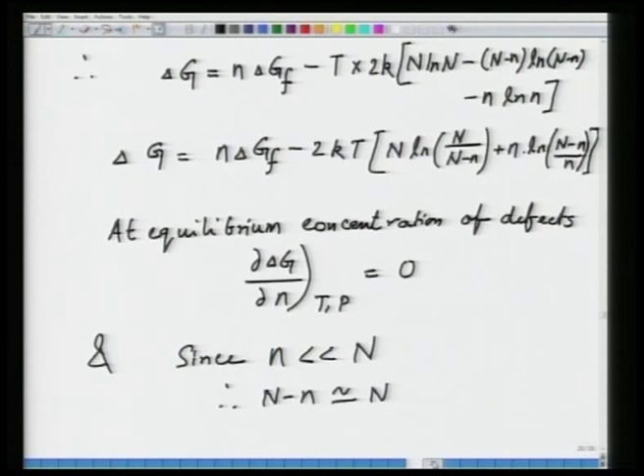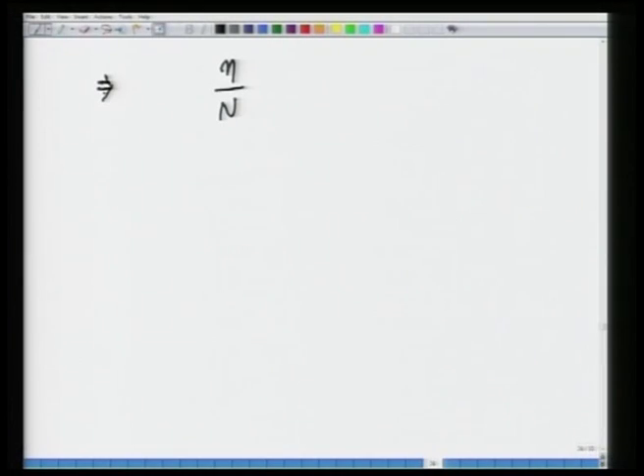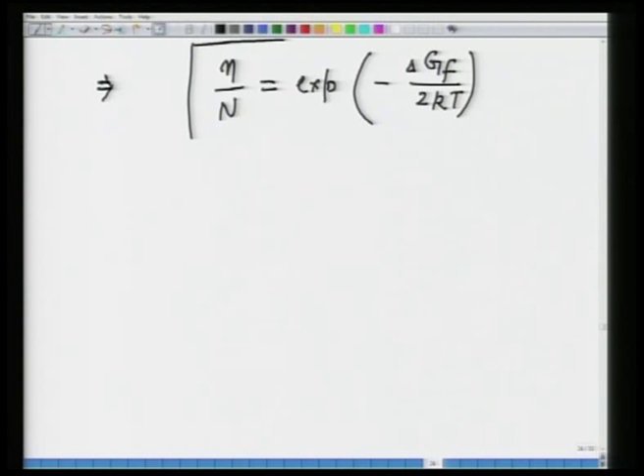So, when you differentiate, what you will find is this. If you do that exercise and replace capital N minus small n as almost equal to capital N, then you will find small n. So, if you differentiate the free energy equation with respect to n, it is a very simple differentiation, this would lead to exponential of minus delta G_F divided by 2kT. So, this is an important expression.